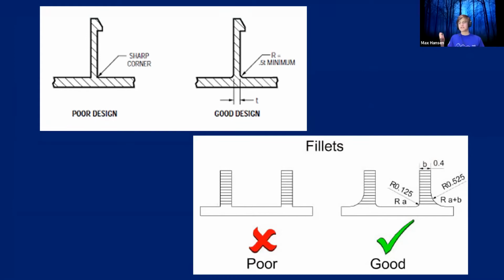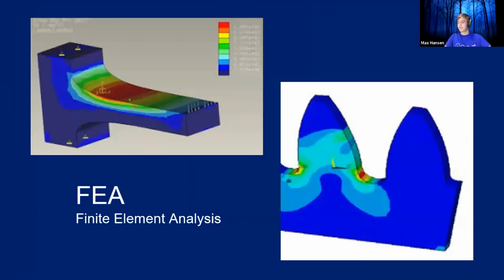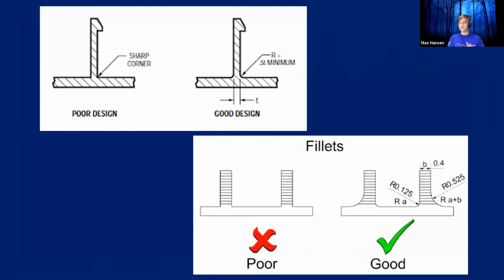Again, on the bottom, you can see the left side is a very poor design, no fillets. Those hands are going to break off very, very easily. And on the right side, you can see the inner fillet is smaller than the outer fillet. So the arms are going to have much more strength when pushed outward than they are when pushed inward, but that's okay because the part was most likely designed for that. But even including those small fillets makes a big difference.